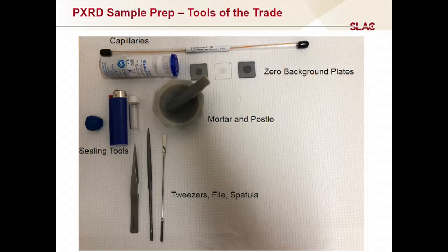I am happy to measure things in a zero background plate. However, I prefer to measure things in a capillary anytime I can get away with it. And there are 2 reasons for that. Well, maybe more than 2. One is preferred orientation doesn't tend to be as big of a problem in a capillary. If you're just kind of letting powder flow down into the bottom of a capillary, it has to have a pretty dramatic crystallite shape before it's going to align in a certain way. And so you tend to get a good random orientation of your powder that way. It's also easy to spin a capillary while you measure it, which gives you a better powder average. It's the same idea as rocking, except taken to the extreme. So you can get very good powders out of that.